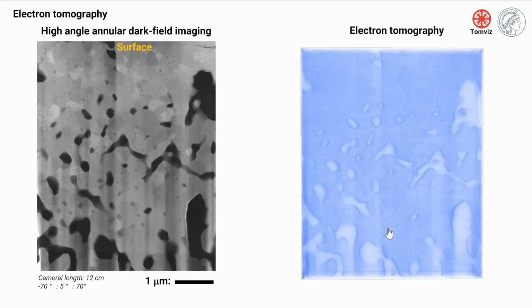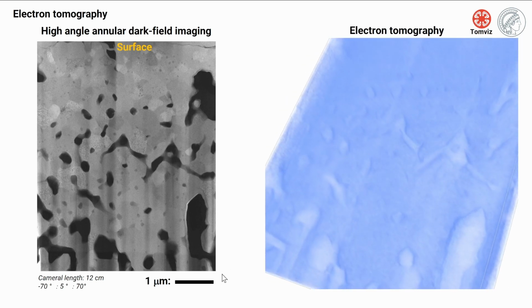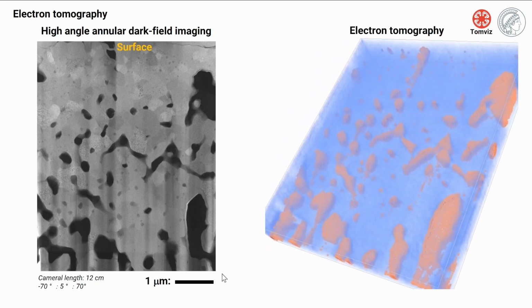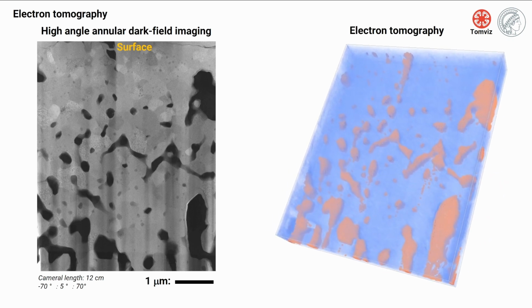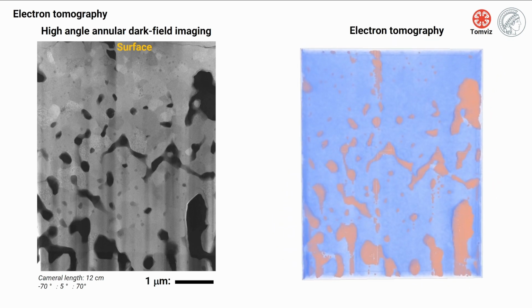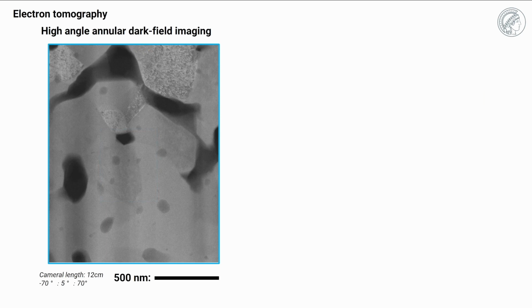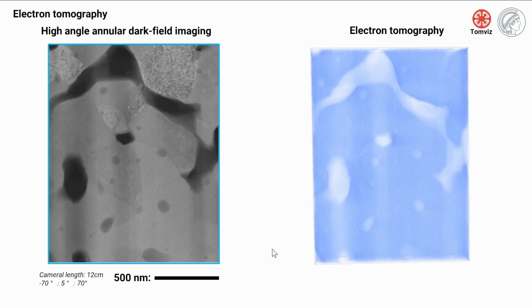We also look at the characteristics of these pores that form at very high resolution. This is high angle annular dark field imaging. And through this electron tomography, we aim to study not just the dispersion, the distribution of the pores, but also how they are connected. That means how they percolate. This is very important information that we need to better understand how the gas transport in the material takes place. Here you see a complex polycrystalline structure around such pores that form.